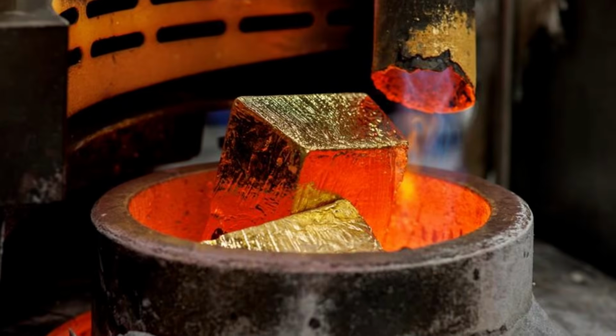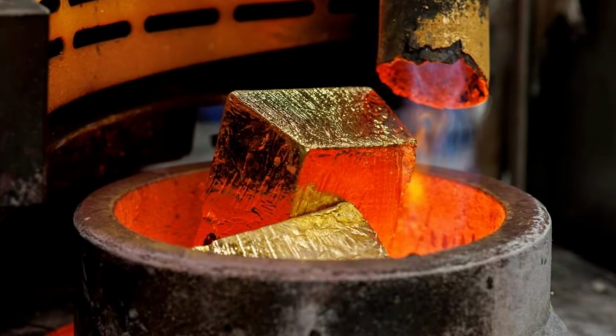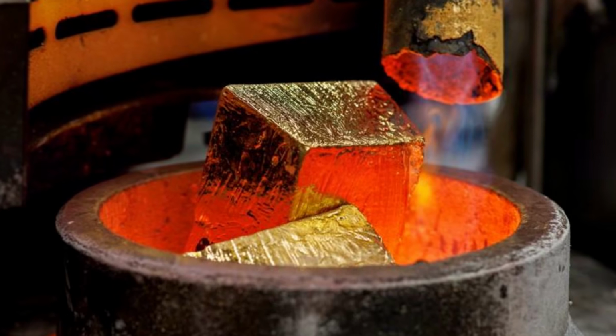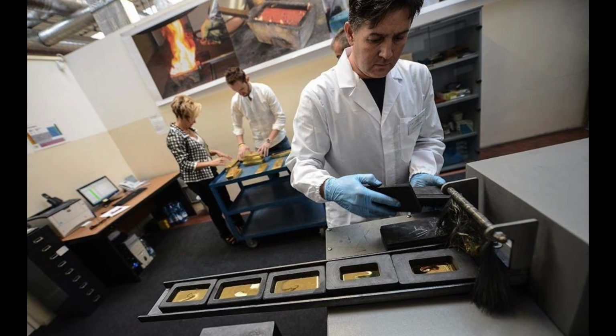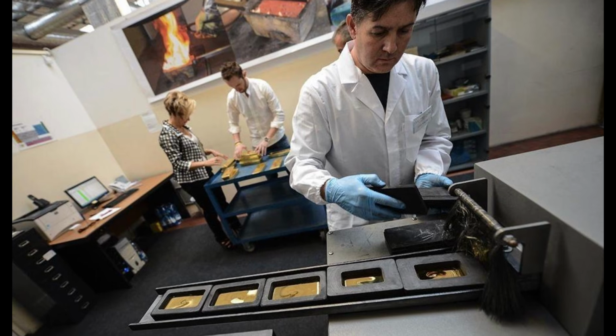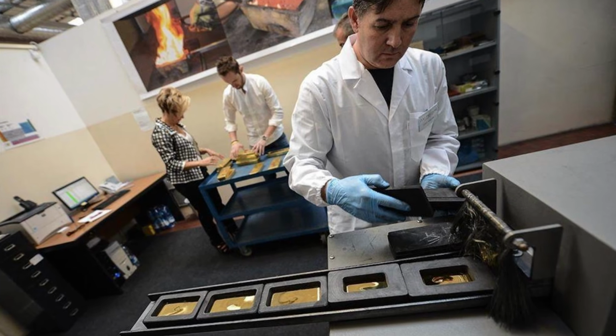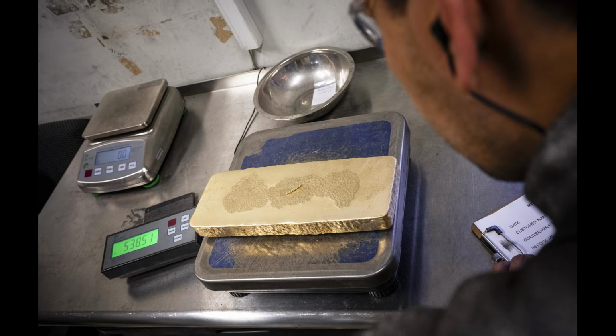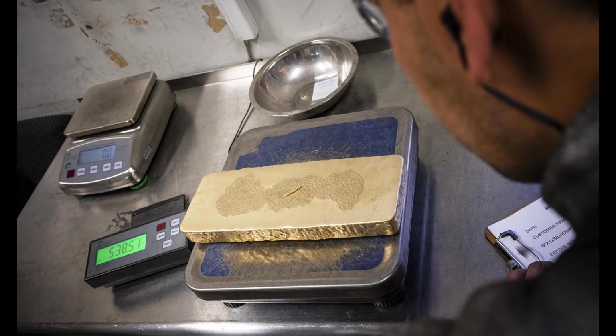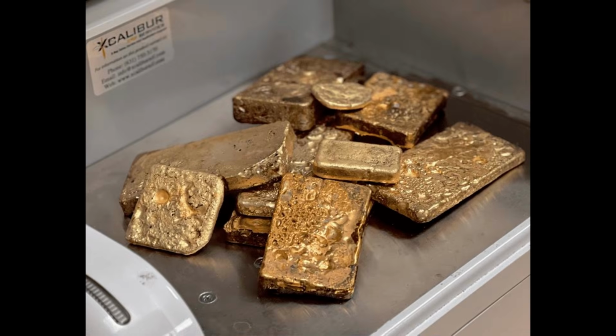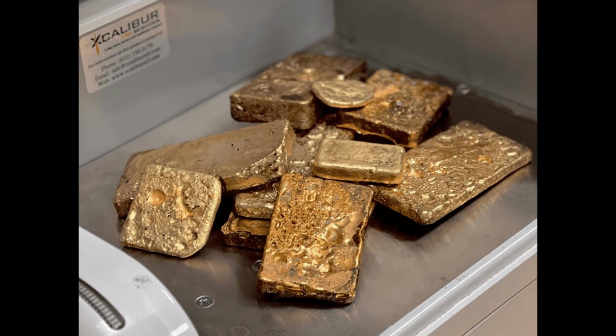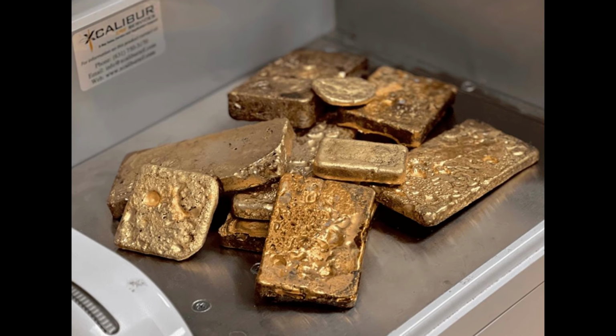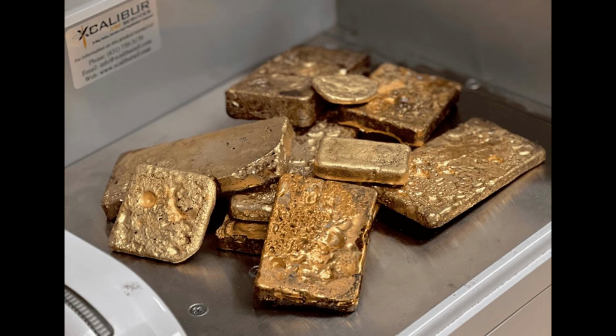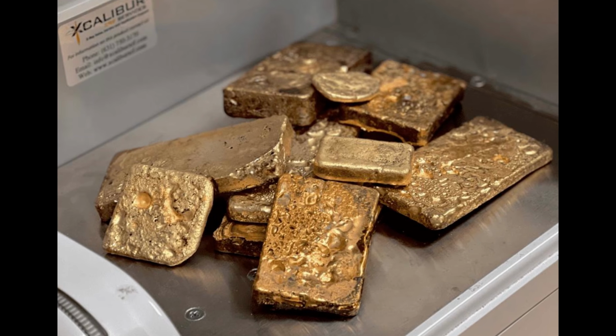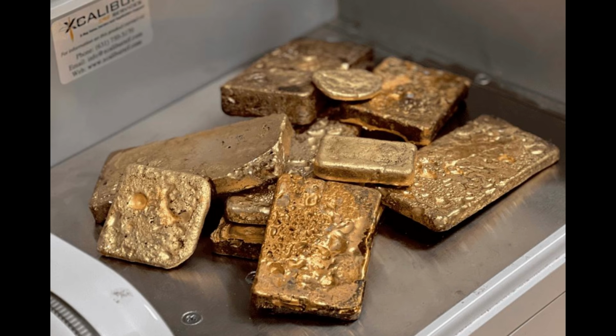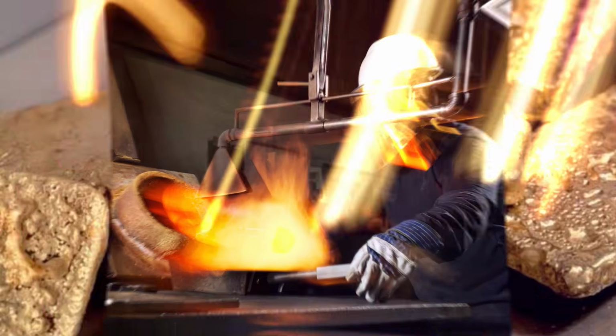The metal glows orange, folds across the mold, and begins losing heat almost immediately, but casting introduces its own failure points. As gold solidifies, it contracts. The surface may develop ripples, depressions, or characteristic cooling patterns. Some are normal features of a cast bar. Others may indicate porosity, inclusions, irregular filling, or a defect that affects acceptance. A cast bar is not expected to resemble a perfectly machined block. Its surface records the physical behavior of molten metal during cooling.